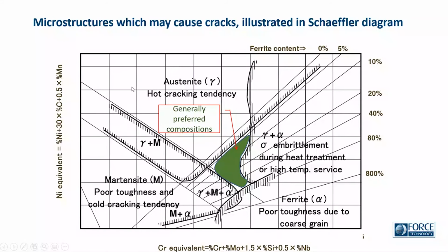Example of welding stainless steel. We have the Schaeffler diagram, and we can define some problematic areas from welding different kinds of stainless steel, or even low alloy steel. It's a diagram where we have the alloying elements which would form ferrite in the chromium equivalent. The more of that, the closer we get to the full ferritic material. And over here we have the nickel equivalent, the elements which would support austenite.